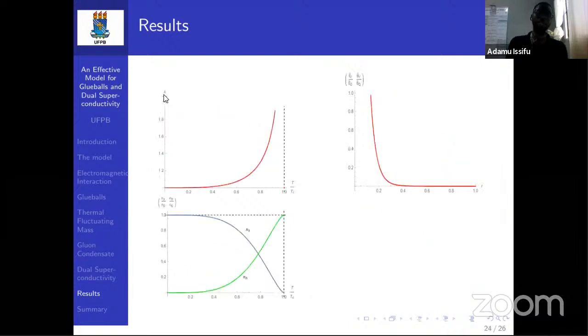Now, this is the London penetration depth we calculated from our model framework. We realize that here we have a straight line. Where we have the straight line, that is the diamagnetic behavior of the vacuum. And here, where it starts rising, that is where we have the mixed state for type 2, and then the intermediate state for type 1 superconductors. And then this is the Meissner effect exhibited by both the electric and the magnetic source at the vacuum of the potential.